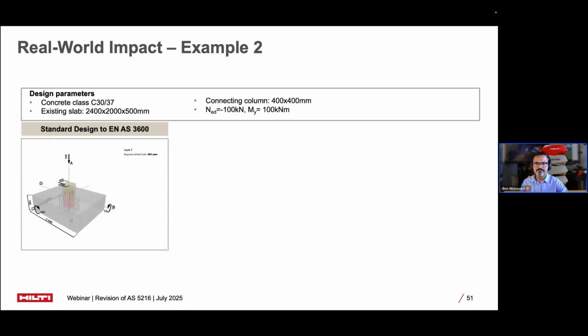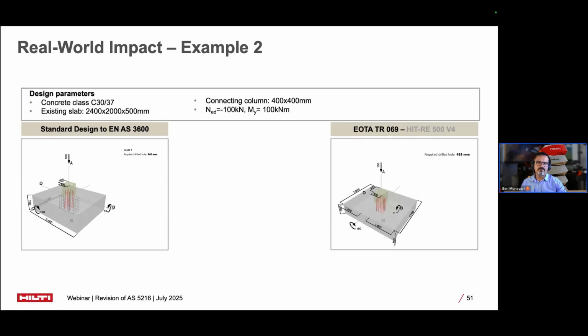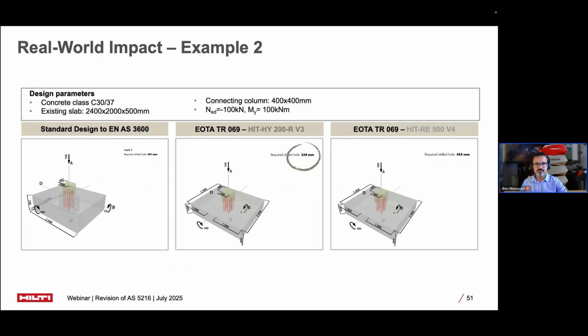Let's go to the second example. The second example demonstrates a column to foundation connection. A standard equal to casting design requires 661 mil depth. If we change to RE500V4, then depth will be reduced to about 453 mils. And if you go to HY200V3, now we achieve 330 mil depth, which is a 50% reduction. As you can see here in this example, HY200 gave us a better result because this is a different design, and specifically it's because we have a different confinement. So with different confinement, either RE500 or HY200 can give us a better result.